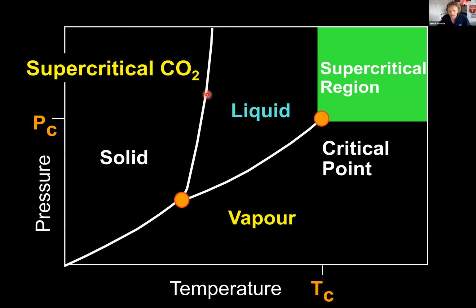We get some liquid CO2, and this is in equilibrium with gaseous CO2. And when we raise the temperature and raise the pressure, you can see the liquid is expanding, the gas is compressing, and eventually the densities of the two become the same. And at that point, the meniscus disappears. And this is a supercritical fluid. And then if I lower the temperature and pressure back down again, you can see we get the phase separation, and we go back to liquid CO2 and gaseous CO2. And what's exciting for us is that when we're at the critical point, we have a supercritical fluid, which is neither a liquid nor a gas. And so this is a very important aspect of the way that we describe the fluids.